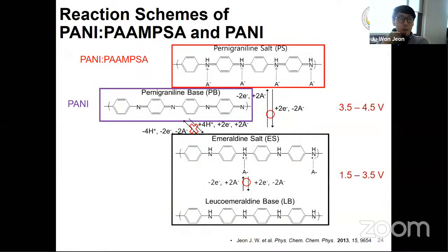So this is the reaction scheme of the PAAMPSA and polyaniline. Polyaniline and PAAMPSA can utilize this kind of reaction, actually between leucoemeraldine base and emeraldine salt. If you increase the voltage, this leucoemeraldine base is converted to the emeraldine salt, and then beyond 3.5 volts, this polyaniline is irreversibly converted to the pernigraniline base by losing the proton here and losing the electron. It cannot be converted back to the emeraldine salt form because there is no available proton in the electrolyte.